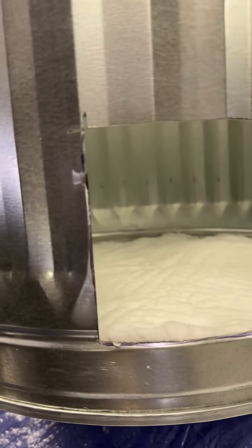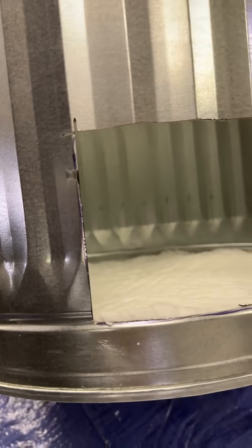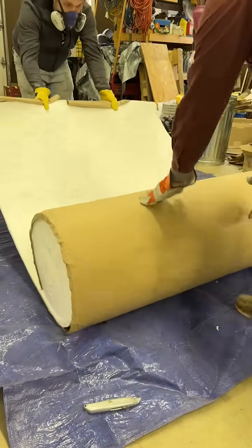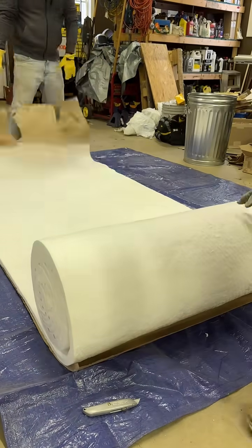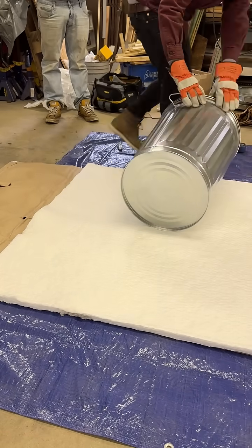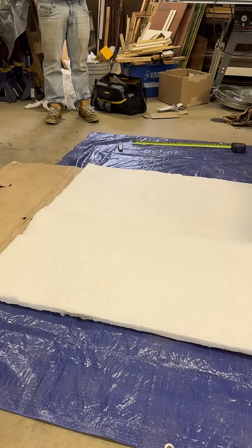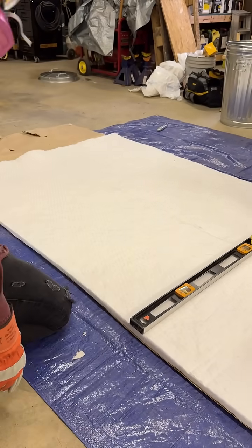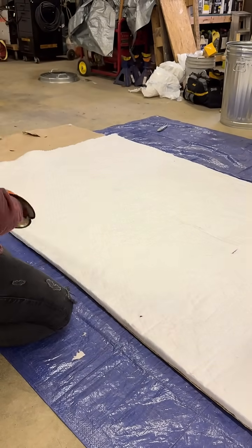Now that the base fiber is set in place, we're going to focus on the interior fiber of the kiln. Typically, people fire Raku at cone 06, which is 1850 degrees Fahrenheit. The ceramic fiber we're using today is Durablanket, which is actually graded for 2400 degrees. With that being said, we'll definitely be within the safe range for firing Raku.